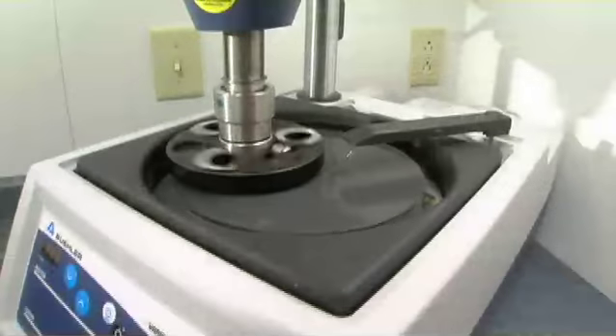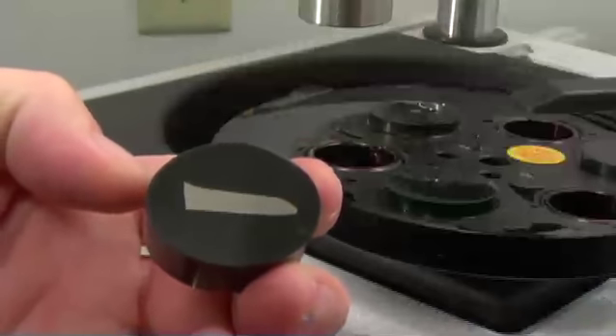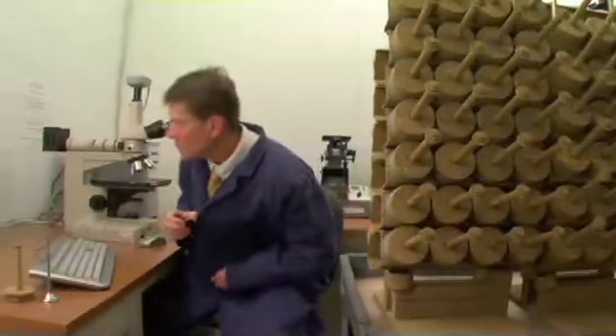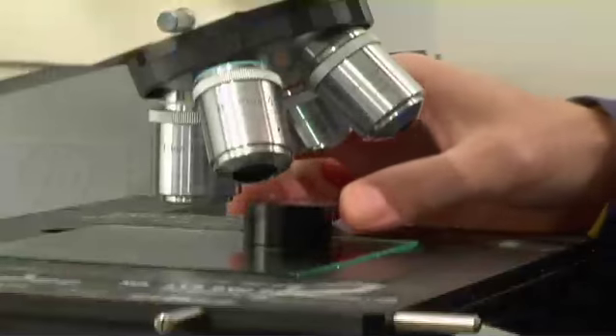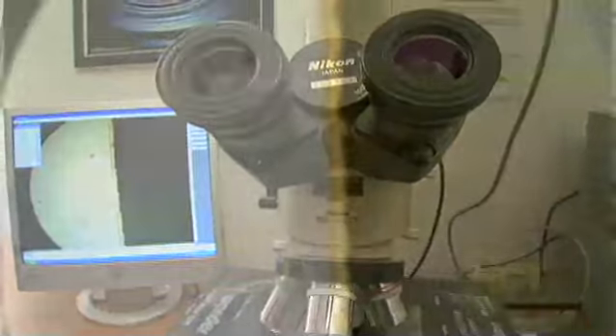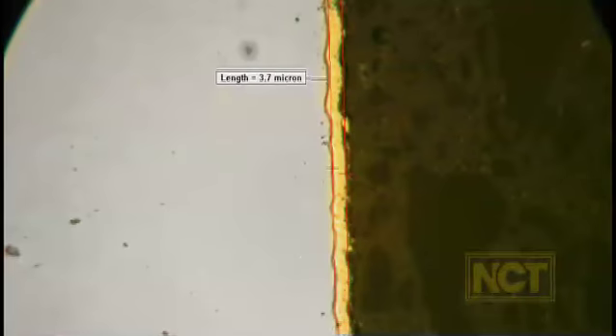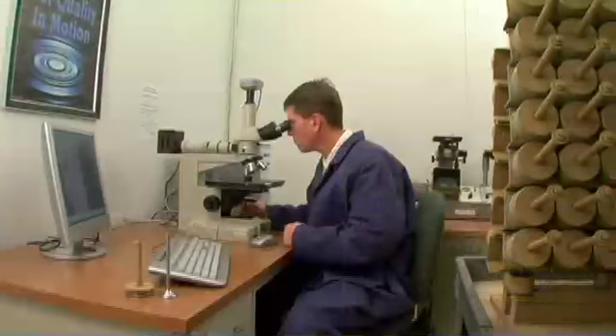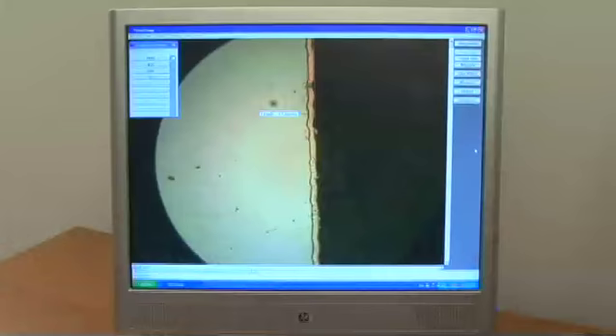Our technician chooses a sample. The part is sliced to expose a cross-section of the treated metal. It is then placed in an examination medium which is polished. The cross-section specimen is then reviewed using our image analysis system. The technician examines the sample to determine if there are any irregularities. This PVD coating is uniform and consistent and has the proper thickness. The process is so precise that we can consistently produce a layer that is 1/10,000th of an inch thick, repeatedly.